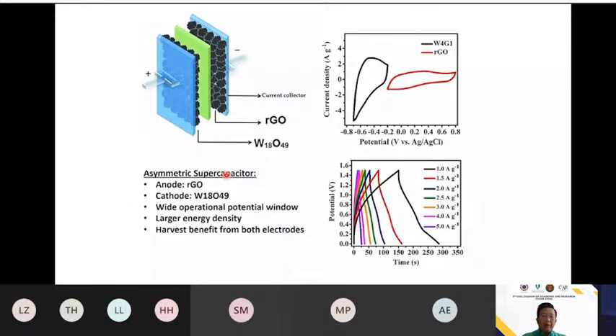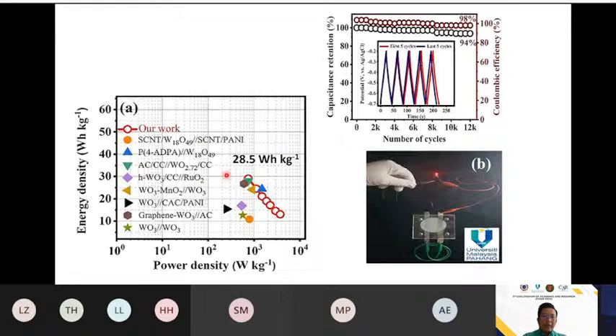And then we form it into the real asymmetric supercapacitor device because we want to test the performance. You can see that by incorporating one side with the tungsten oxide and graphene, we are able to get the energy density of 28.5. That's the highest among all the tungsten oxide material that has been reported so far. And it is also stable up to the 12,000th cycle that we keep on running the charging and discharging process. It still maintains the retention up to 94%.